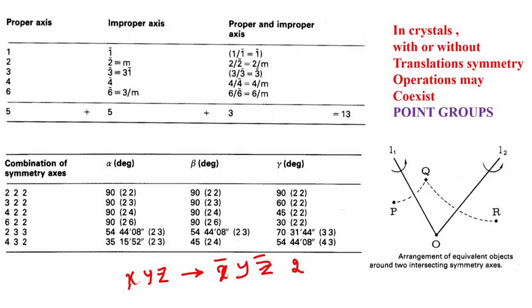In case we have a 2 bar symmetry, that means we operate a twofold, and that twofold operation will now undergo a center of symmetry inversion. So, there is an inversion center, and x, y, z is no longer staying at minus x, y, minus z, but it goes to its corresponding inversion center operation. That means, minus x goes to x, y becomes minus y and minus z becomes z. Now, this operation is the operation of a mirror (m) symmetry,